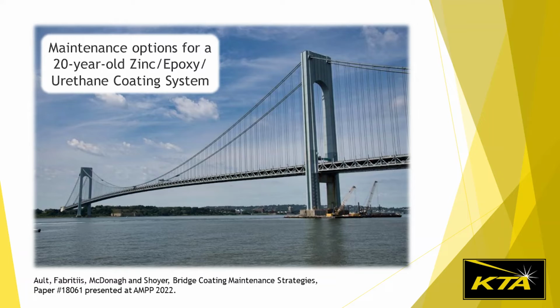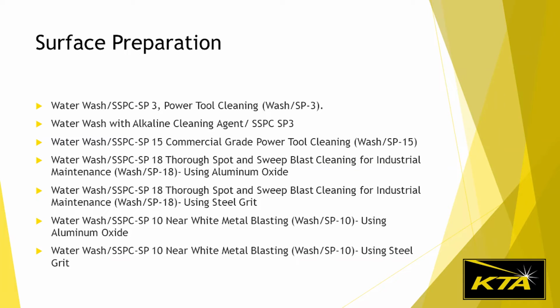The structure here is the Verrazano Narrows Bridge. It's owned and maintained by the Metropolitan Transportation Authority. It connects the New York City boroughs of Staten Island and Brooklyn. The structure was recently painted with an SP18 system. For all of you out there who aren't paint nerds, an SP18 is a thorough spot cleaning with sweep blasting. So basically you're spot blasting and priming the corroded areas and then sweep blasting the good paint to remove loose material and abrade the surface for an overcoat.